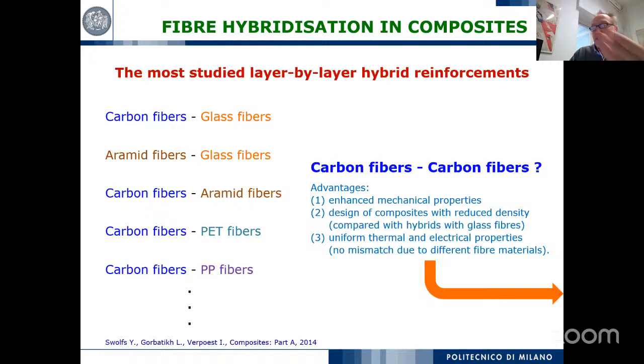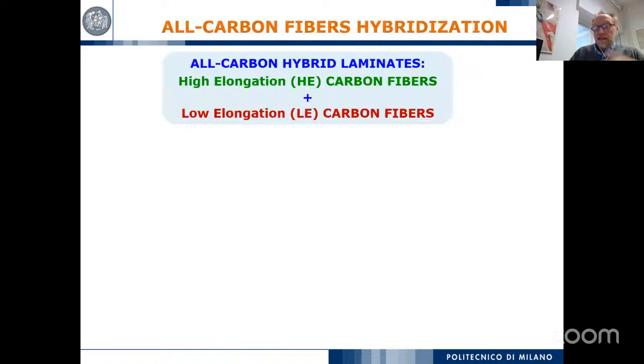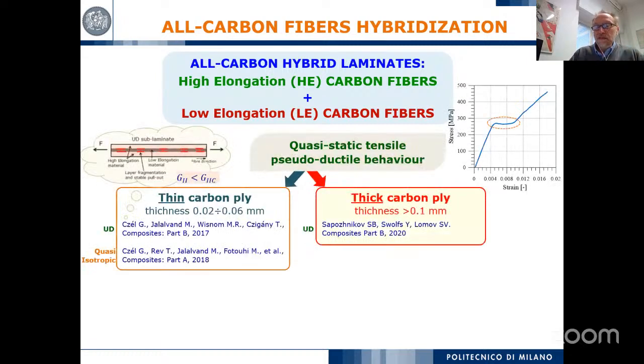And so this is the reason why some research groups work on this hybridization, and this is what I'm going to present to you, using the same material for the fiber. One fiber has high elongation, one fiber has low elongation, and this helps us to create this progressive damage mechanism that leads to pseudo-ductility. In the literature, you can find good work related to this all-carbon fiber hybrid laminates that are mainly focused on thin ply, because the thin ply allows you to create this sequence of damage modes. And so you have quite a number of works on this with thin ply.